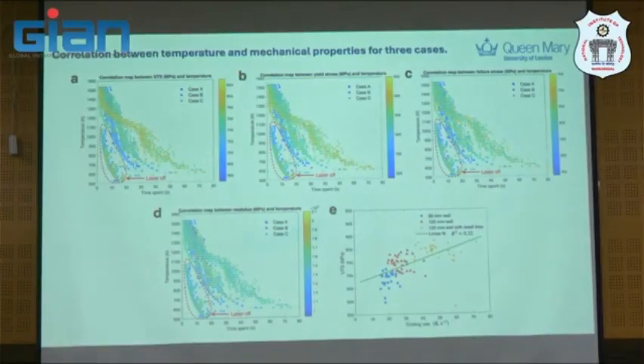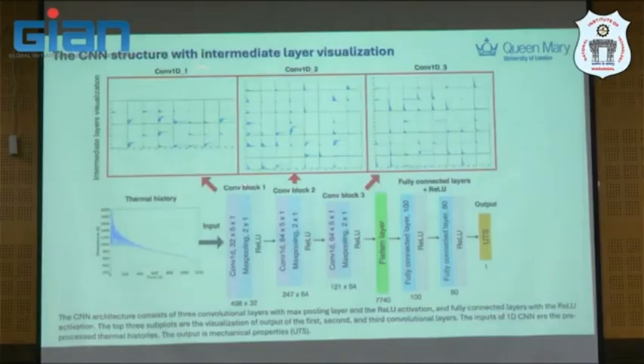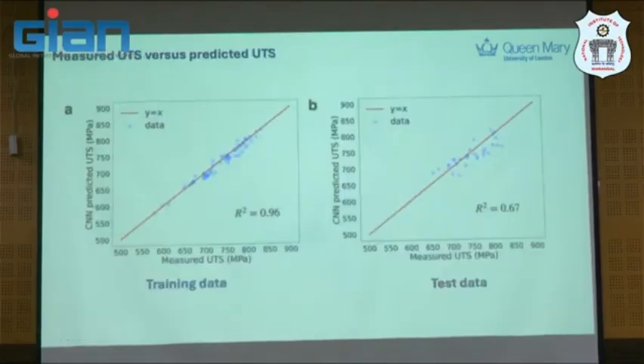And I will show you later that. And you will see here the peak temperature has a significant influence on the property. That's why we have to control this one. And then based on this structure, with the intermediate layer visualization here, in different conditions, you can actually predict the UTS, compared with the CNN model, measured and predicted.